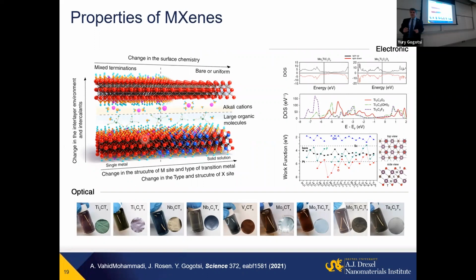So to summarize this part, what do we have? We have this very large family of materials, with scalable production, where we can control properties by changing or adding surface termination, by selecting the number of layers, the kind of transition metal, carbon, nitrogen, or a mix thereof, mixing different M elements or X elements, making solid solutions. But you can also intercalate ions and molecules between the layers. You can also, of course, chemically attach various moieties to the surface, again, not killing conductivity and thickness. So there are so many modes of design. And of course, it changes the electronic structure.